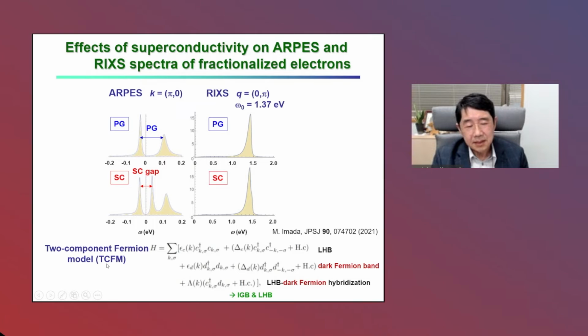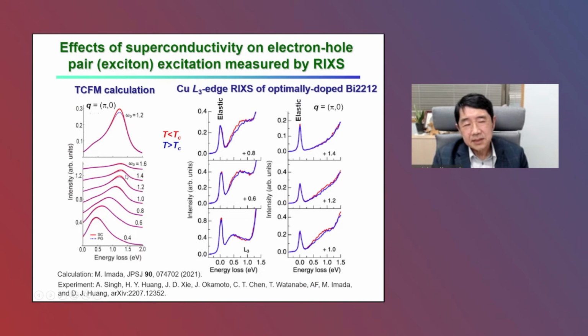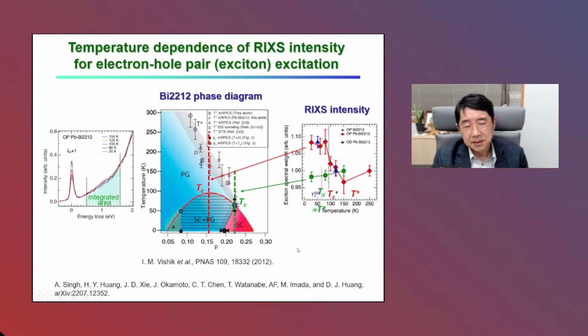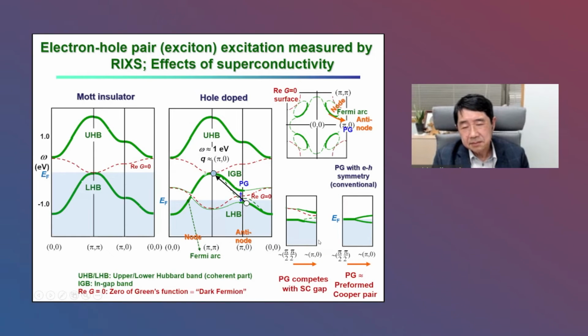So this is a calculation of ARPES at pi zero. Probably this is well known, but the RIXS at pi zero and finite energy. This is not very clear, but there is an enhancement in the superconducting state, which is sufficiently large to detect experimentally. And these are experimental data of such electron-hole pair excitation at an energy of about 1 eV and momentum pi zero. And these are quite well explained by simulation. Okay, we have made a detailed temperature dependence study.